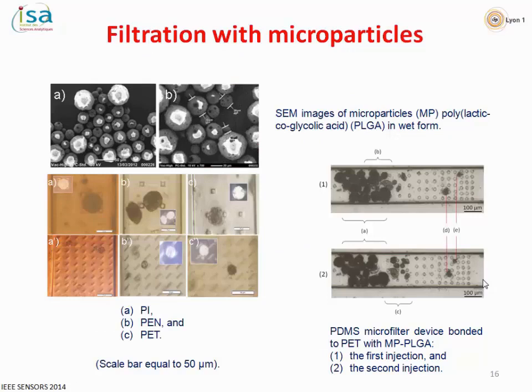Well, to test our microfilters, we use different sizes of nanoparticles, magnetic particles, and we can see here for the first part the microfilters made on PET, and we can see that depending on the size of the nanoparticle that we have injected, we can select at the end what we would like, and it depends on the size between pillars. Because, for instance, here we are using micro, but we are developing nano pillars using vinyl. And we can see at the beginning here, just to compare, it's here. However, it moves. That means at the end, we will only have this kind of particle to analyze with electrochemistry.